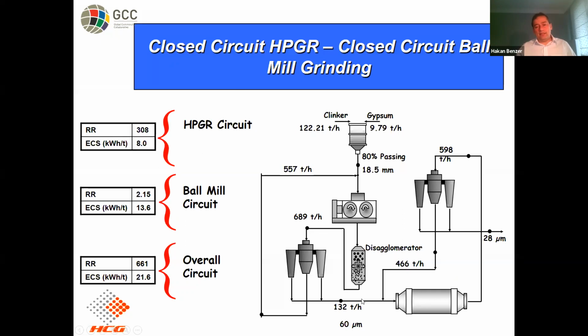Of course, in this case, it was not sufficient for the final cement to produce the required strength. So the ball mill with the air classifier is used to grind from 60 micron down to 28 micron. To achieve this reduction, we are spending 13.6 kilowatt hours per ton. So in total, it is 22 kilowatt hours per ton from a starting point of roughly 20 millimeter down to 28 microns. But the majority of the work is done with the high compression system here.